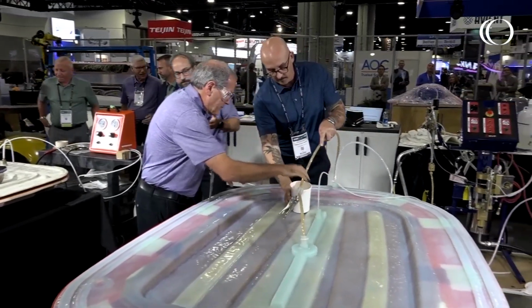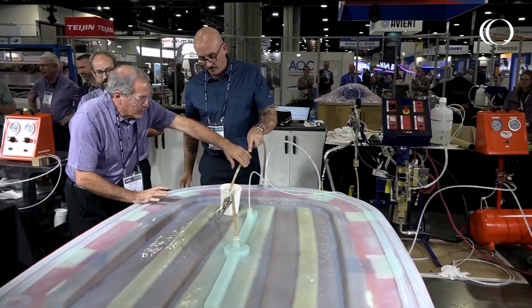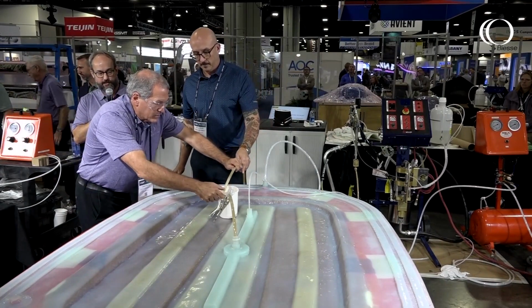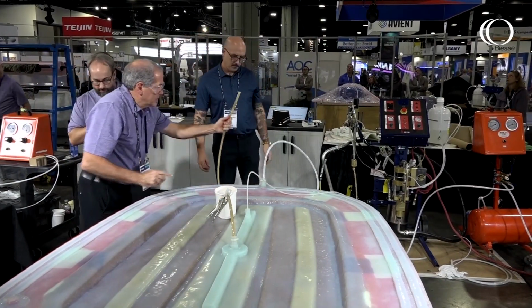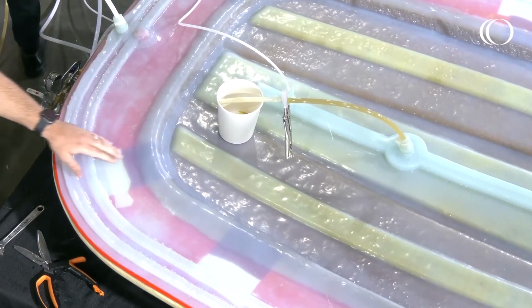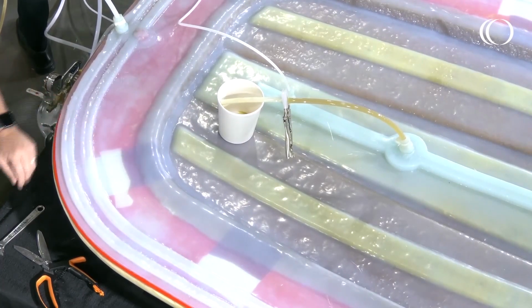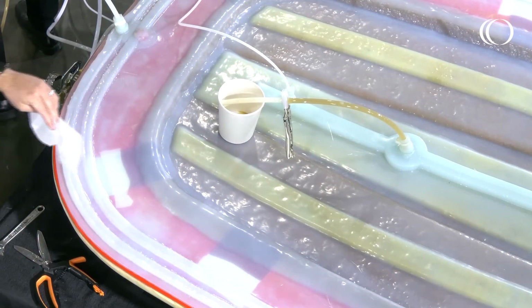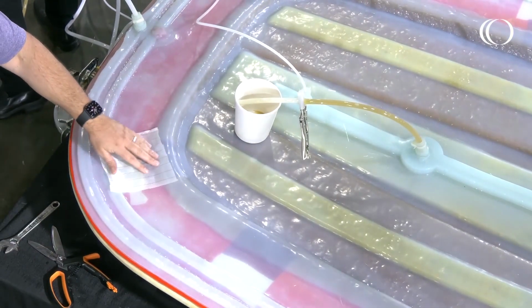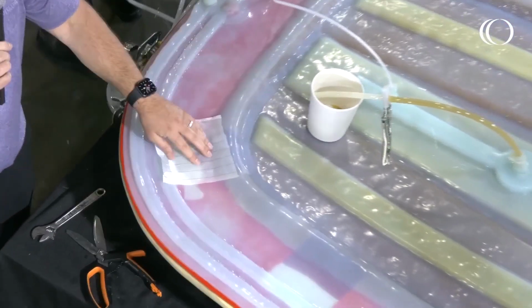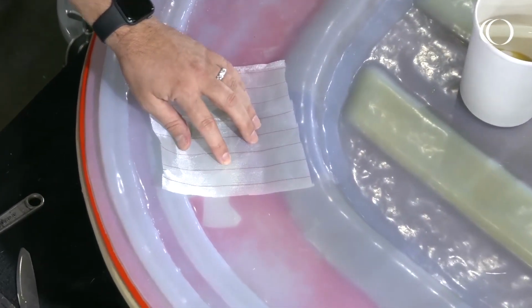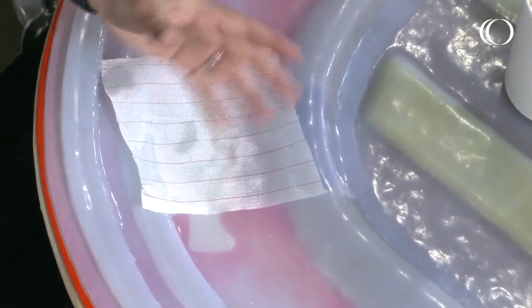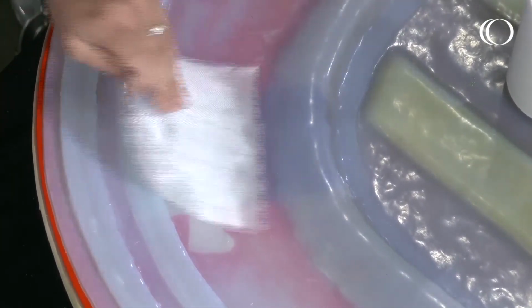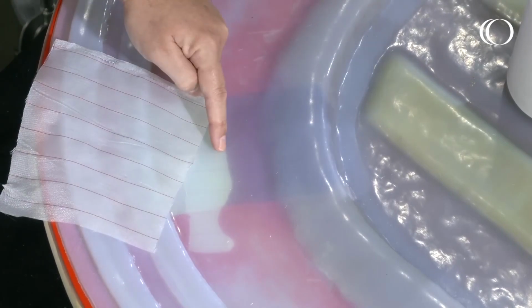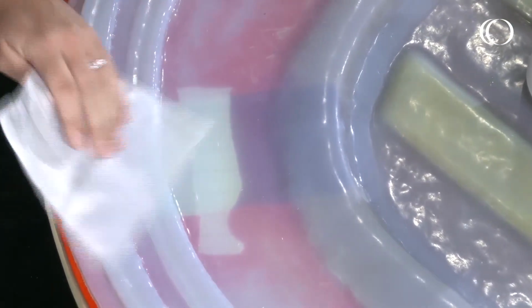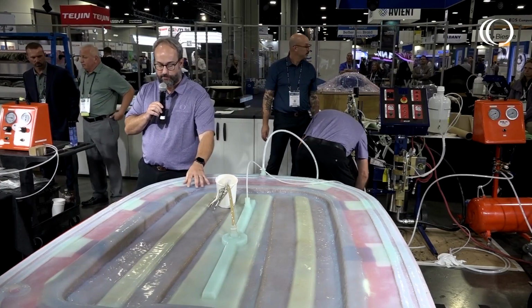And it looks like our silicone bag part is finished. So we clamp the feed line. We're going to maintain vacuum on the part. I think Dan had probably mentioned we have breather strips. In this case, we're using peel ply. It's just any fabric that will flow air, but it has low permeability, so it slows the resin down because we don't want to suck the resin back out of our part. So you can see once the resin hit the peel ply, it really slows down. And then our resin will gel and cure.